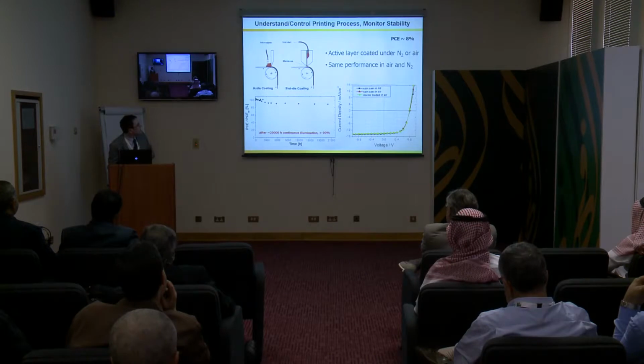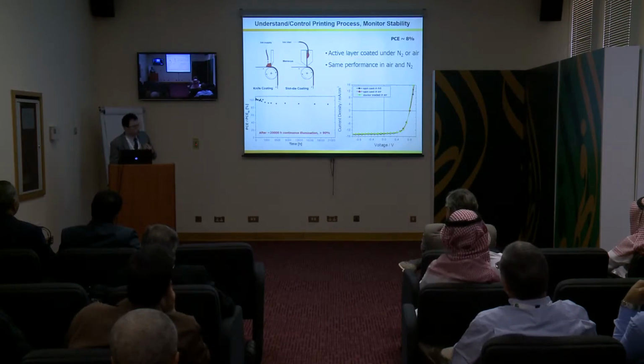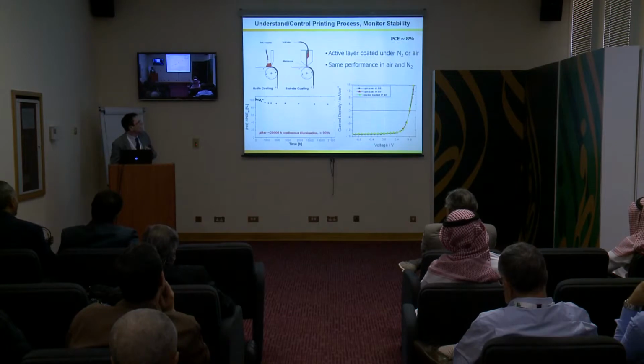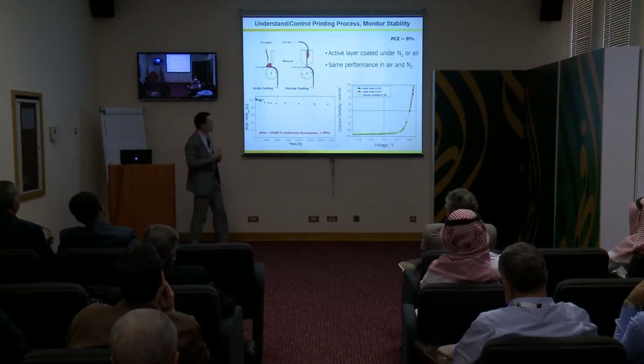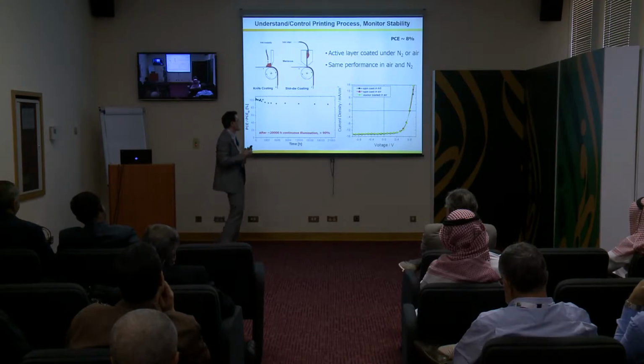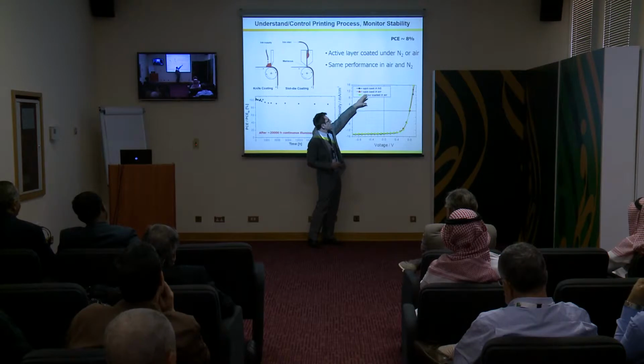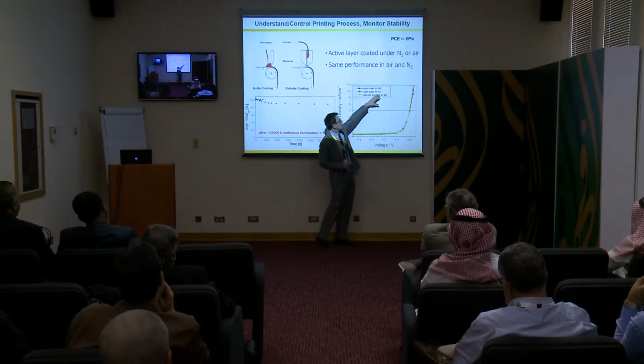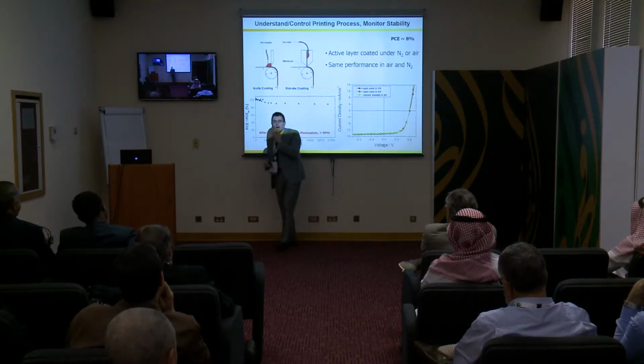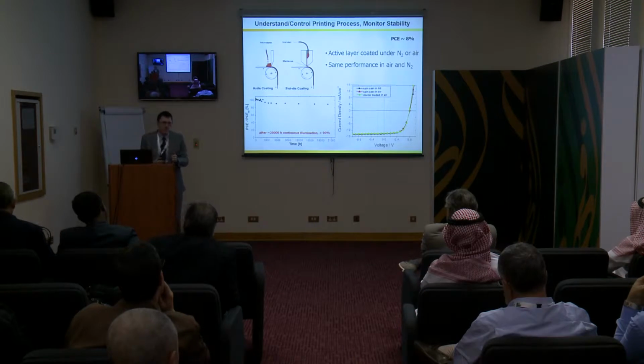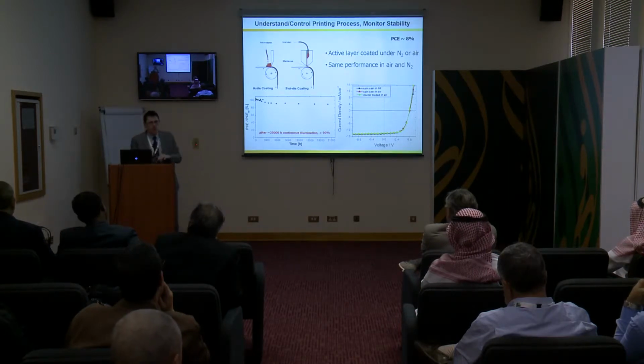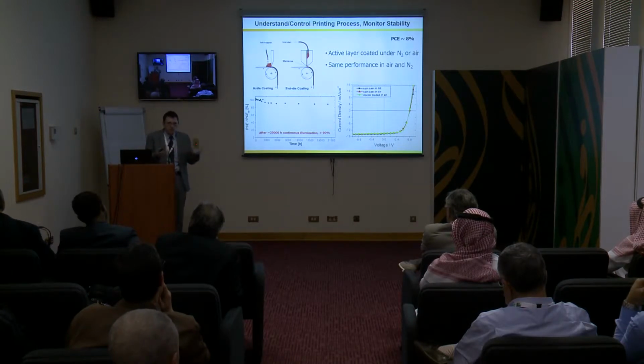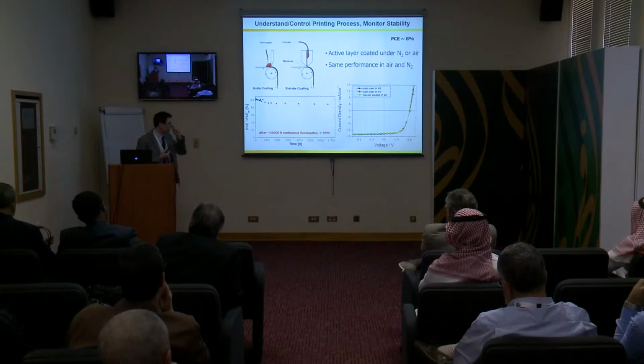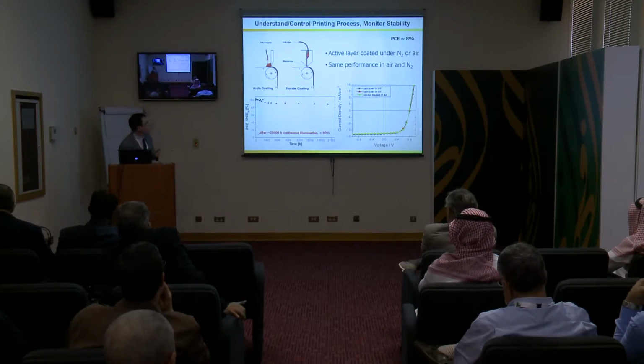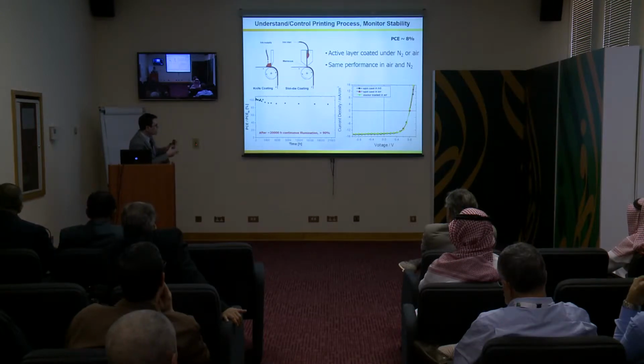Let me skip this. We have also worked on trying to make, this is mostly done at Polyera, modules. Obviously, it's important to achieve high efficiency in a single cell. What is more critical is to achieve decent efficiency at the module level, where the bulk heterojunction blend is deposited not in the glove box, but in air. It is accepted that we must encapsulate the cell. But what is essential is that the cells are produced in ambient conditions, and not all the equipment has to be under nitrogen. This blend can achieve quite decent efficiency, about 8% upon deposition in ambient.